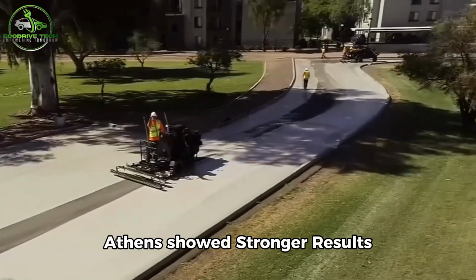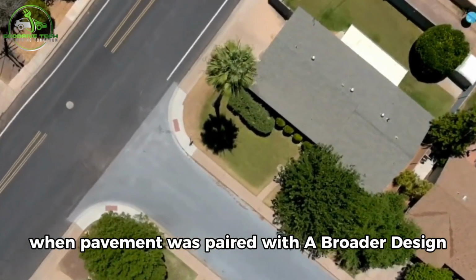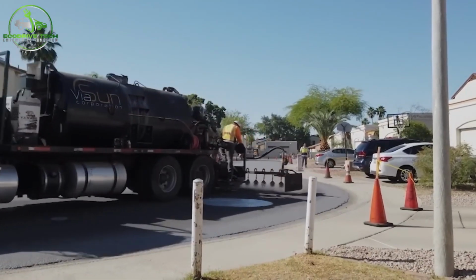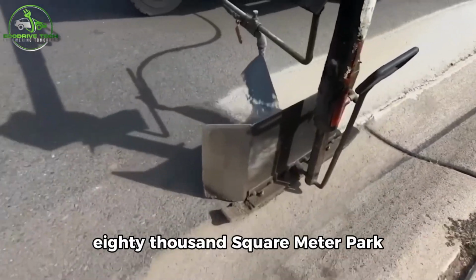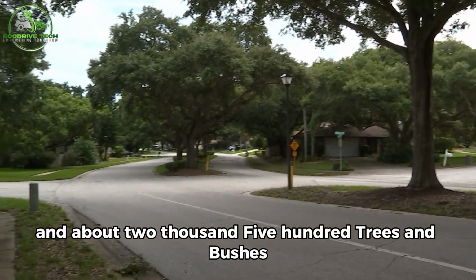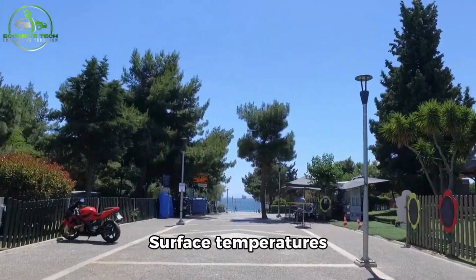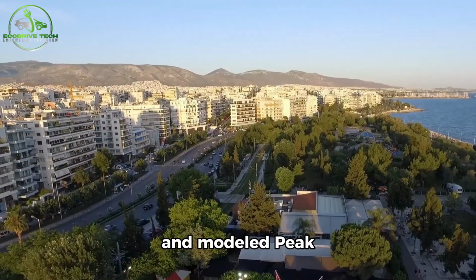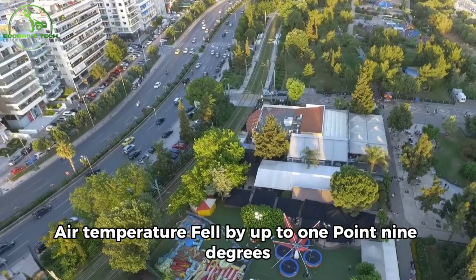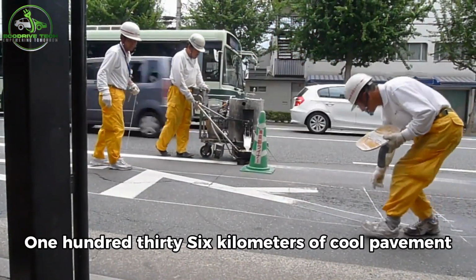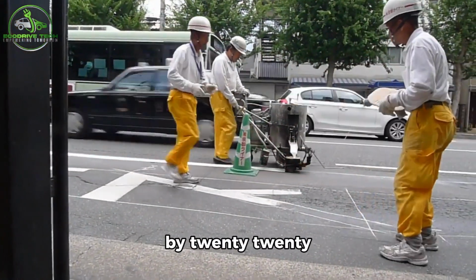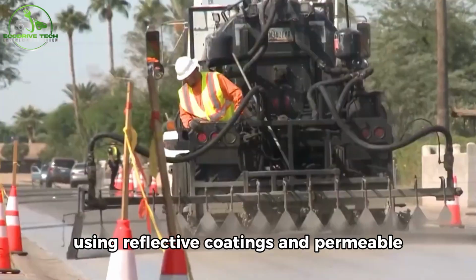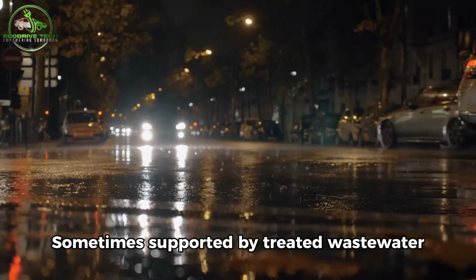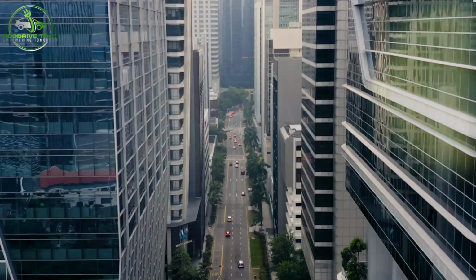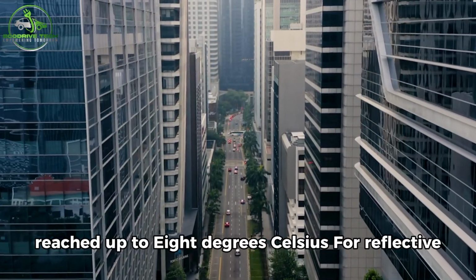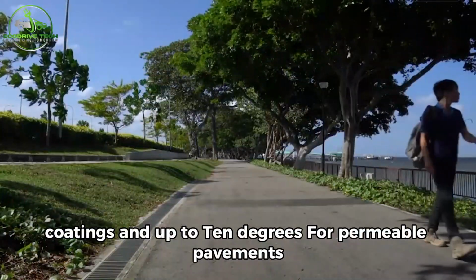Athens showed stronger results when pavement was paired with broader design. At Flisvos Urban Park, cool pavement was combined with an 80,000 square meter park and about 2,500 trees and bushes. Surface temperatures dropped by up to 12 degrees Celsius, and modeled peak air temperature fell by up to 1.9 degrees. Tokyo aimed for 136 kilometers of cool pavement by 2020, using reflective coatings and permeable, evaporative pavements, sometimes supported by treated wastewater. Surface cooling reached up to 8 degrees Celsius for reflective coatings and up to 10 degrees for permeable pavements.